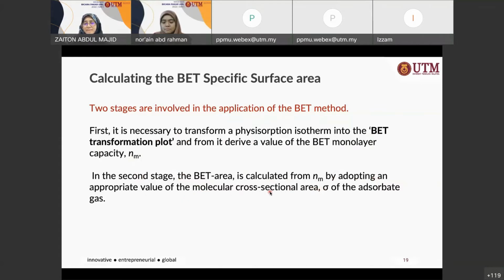So if your adsorbate gas is nitrogen, you have a specific molecular cross-sectional area. If you're using argon or krypton, then you have that value for the molecular cross-sectional area of that gas. So you need to run the gas adsorption, and then you transform it to the BET transformation plot, get the monolayer capacity nm or Vm, and then from there, you calculate the BET surface area.